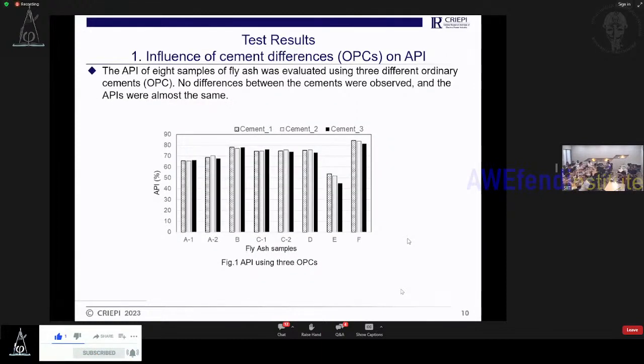Firstly, I show you the test result. This shows the impact on the API value from the difference of the cement. We applied three cements, named cement 1, 2, 3. The vertical axis shows the API, and the horizontal one shows the sample number from A1 to F.